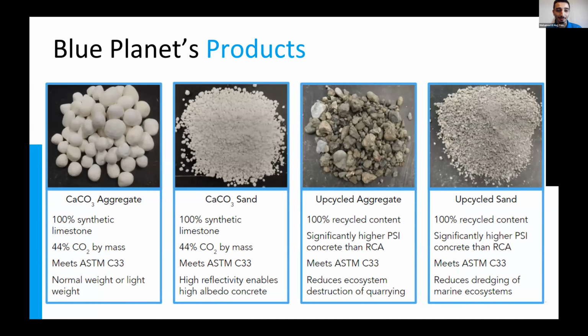So here's my favorite slide. I'm going to go straight into the products. I'm going to start with the two on the right, our upcycled aggregate. In the next slide, I'll show our process, but one of our input materials is demolished and returned concrete, currently at our plant here in Pittsburg, California. With that demolished and returned concrete, we put it through what we call an acid wash. It strips away all that calcium oxide dust that really makes recycled concrete aggregate an issue to develop with. Once we process that demolished and returned concrete, we're left with a liquid. That liquid is an alkaline solution. And to sequester CO2, which is an acid gas, you need a basic or alkaline solution like we've developed after we acid wash this upcycled aggregate.